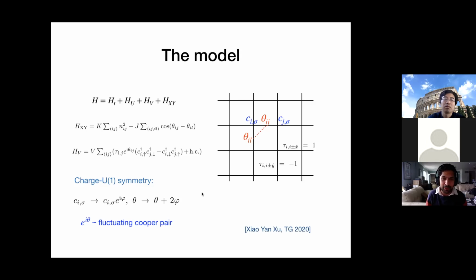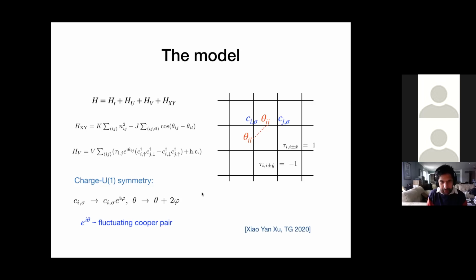Anyone who looks at this model, it must be obvious within a little bit of thinking that it has D wave. So the taus are just numbers, -1 on the y bond, +1 on the x bonds. When J is large compared to K, theta condenses, and you just get BCS mean field theory. So clearly it has D wave order parameter, which is non-zero in some limit. The surprise is not that it has D wave order parameter. The surprise is it doesn't have sign problem. That's the main point.